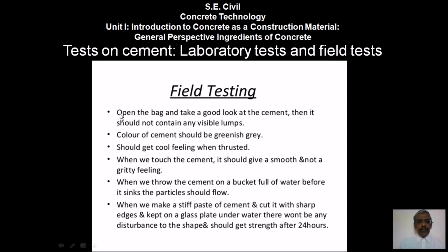In that you have to open the bag and take a good look at the cement. It should not contain any visible lumps. Then the color of the cement should be greenish gray, and it should give a cool feel when thrust by the hand. When we touch the cement, it should give a smooth and not a gritty feel. Another test: when we throw the cement in a bucket full of water, before it sinks, the cement should float on that. Another test: we mix a stiff paste of cement, cut it with sharp edges and keep it on a glass plate under water, then there won't be any disturbance to the shape and it should gain strength after 24 hours.